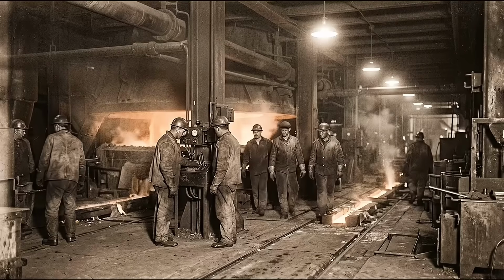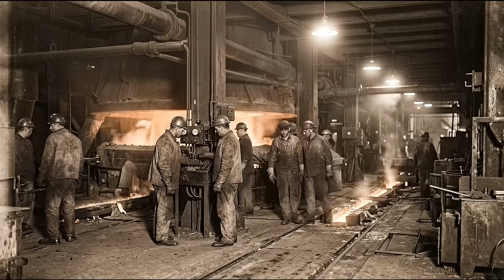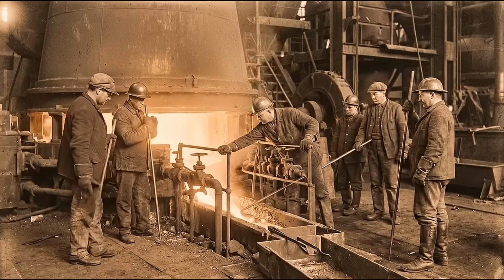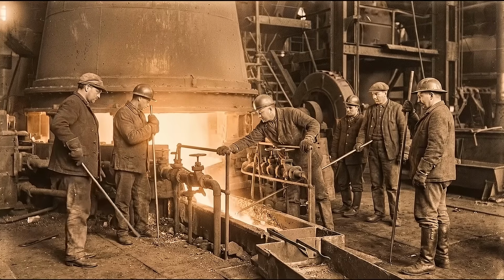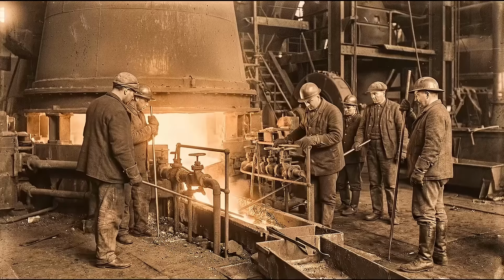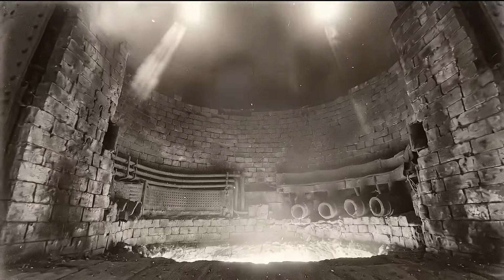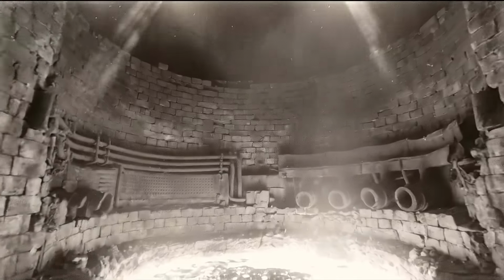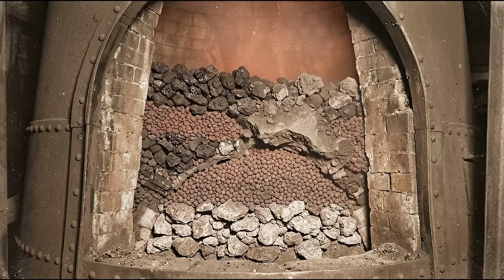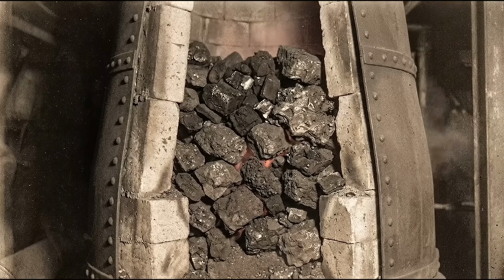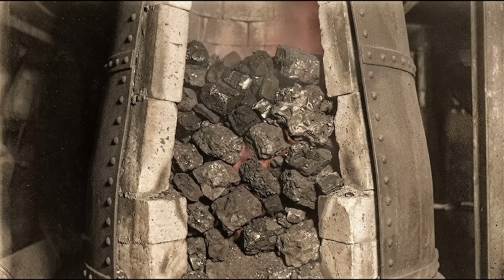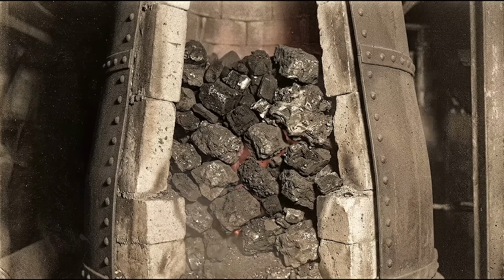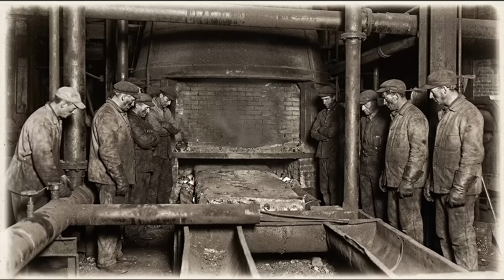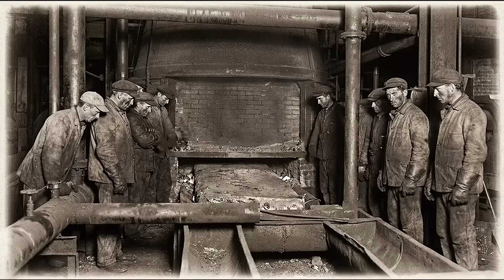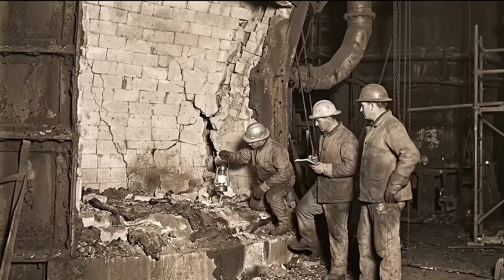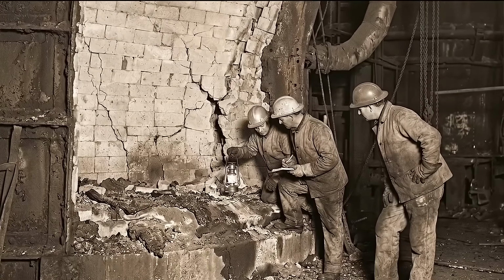The entire operation is staffed in rotating shifts around the clock because the chemistry inside the furnace depends on maintaining a steady state of temperature and material flow. If you interrupt that flow, the molten iron inside the hearth can begin to solidify, the burden above it can bridge and lock up, and the whole thing can turn into a frozen mass of metal and rock that is almost impossible to remove. Shutting one down early, even for a few days, risks a catastrophic freeze-up that can destroy the furnace lining and cost tens of millions of dollars.